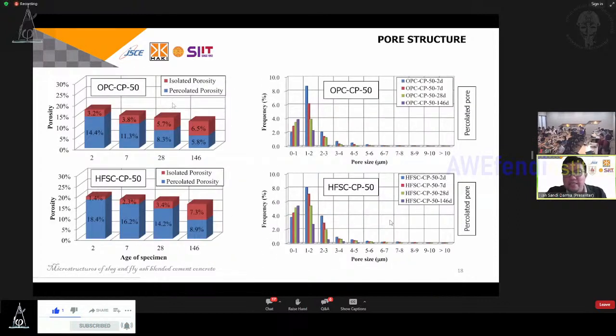And then here you can see the histogram shows the porosity versus curing period. As you can see here, of course, for OPC we will have a lower porosity compared to the fly ash specimen. But again, as you can see, with the increase in the curing period, the reduction in percolated porosity is higher than for the OPC one.